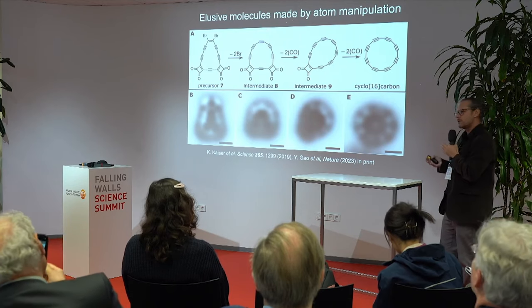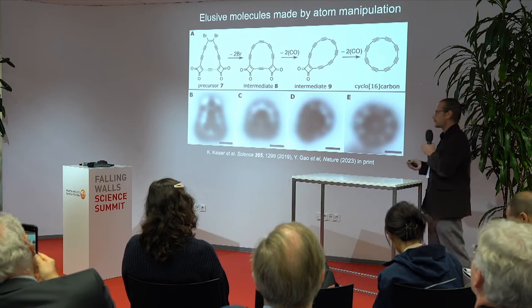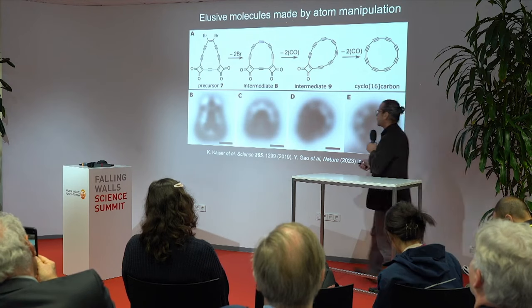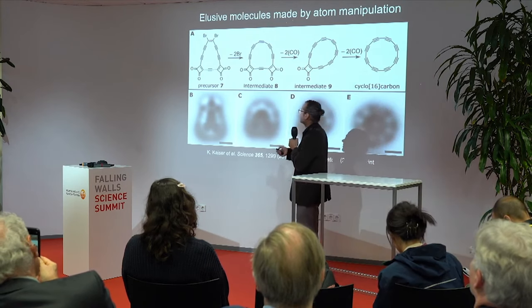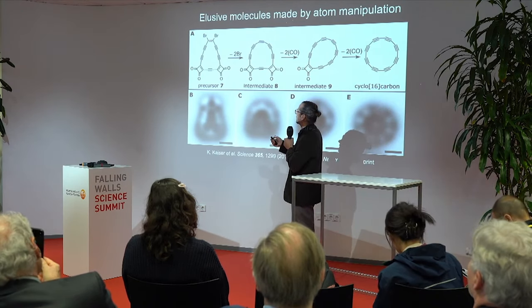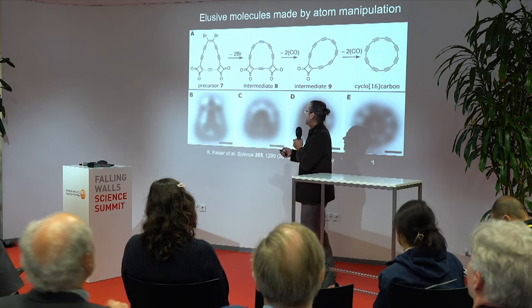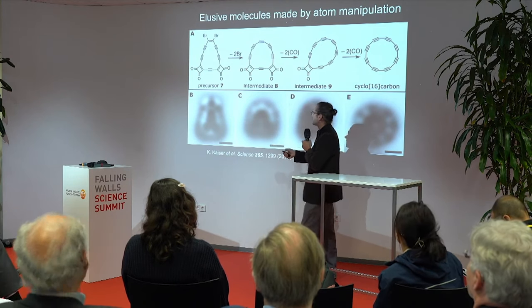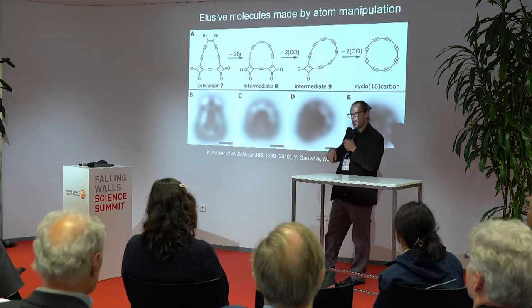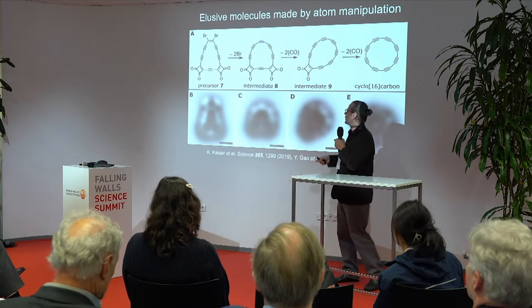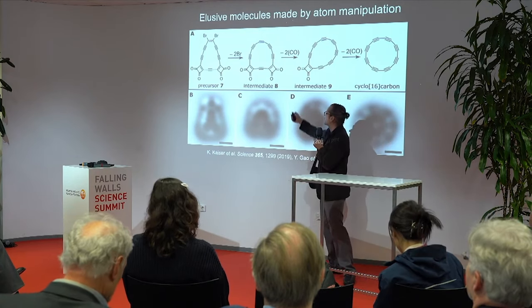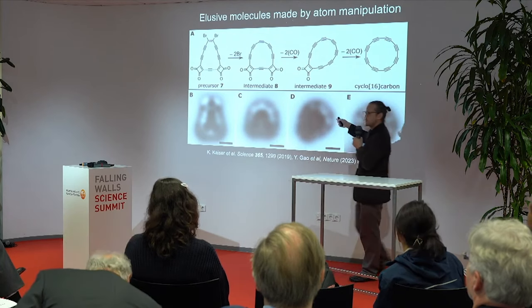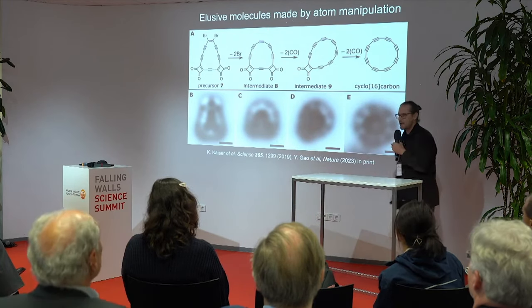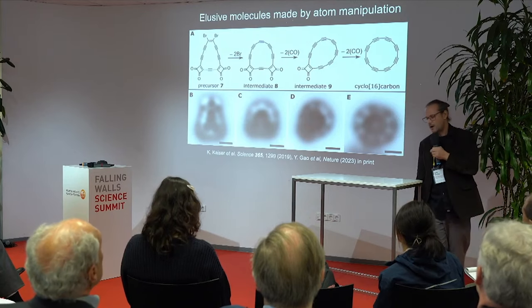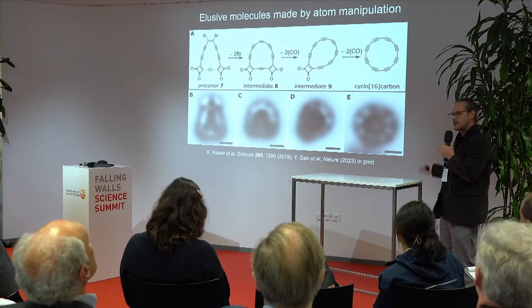And we can make them on our surface again using the tip to do chemistry. Here we get precursors from our chemistry collaborators, and these have masking groups, in this case bromine and CO. And here you see an image of the precursor. And now by applying voltage pulses with our tip on this molecule, we can take off these masking groups and we can make this molecule, and then we make this molecule. And finally, we get this ring molecule. And now we can also study it.